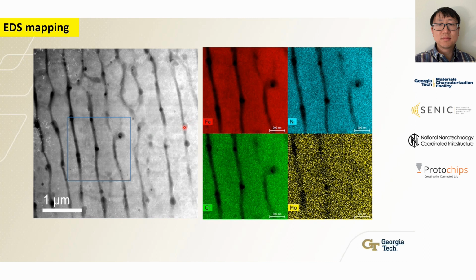One interesting thing is that there are many oxides at the cell network, and this oxide increases in size. Compared to the oxide inside the network, we want to see what the origin of this big dark spot is, and whether this dark spot can increase in size and eventually become a pit. So we need to resolve every moment of the corrosion. So we need something called a time-resolved corrosion test, capturing every second of the corrosion.